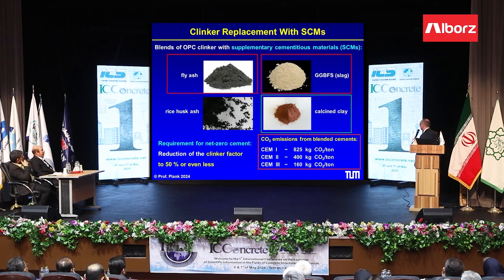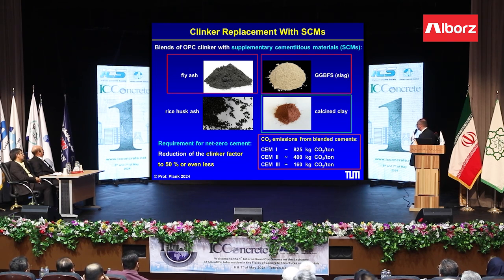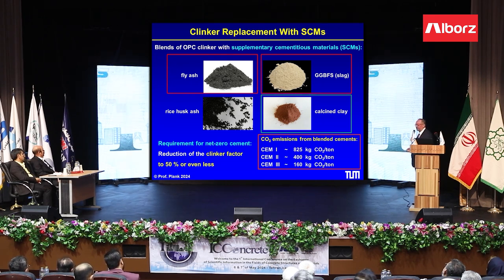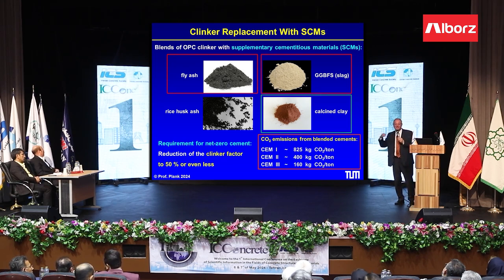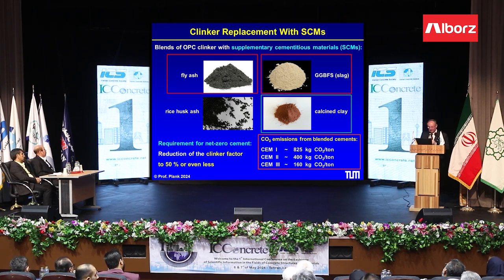The other possibility is that we use pozzolans, as has been mentioned in the presentation before about natural zeolite, and basically reduce the clinker content in the cement by using fly ash, slag, and most recently calcined clay, which has become very popular. By doing so, it is possible to become climate neutral with the cement formulation. We need to be below 450 kilos to be climate neutral, and this is possible. It means the clinker factor in our cement has to be less than 50%. So for the cement industry, you can see this is a very big challenge and a very big change.